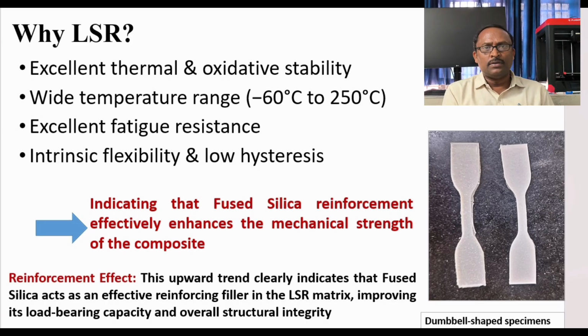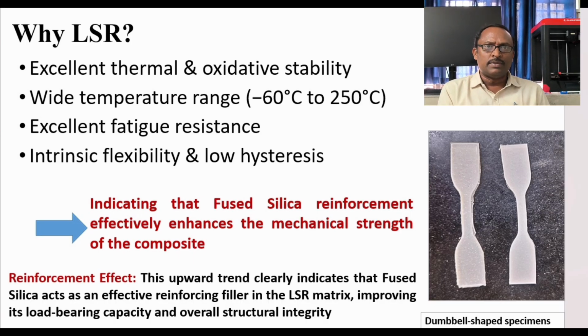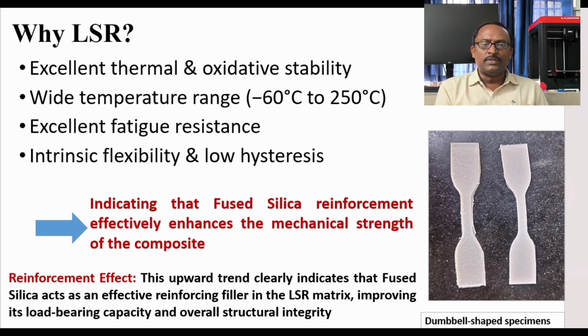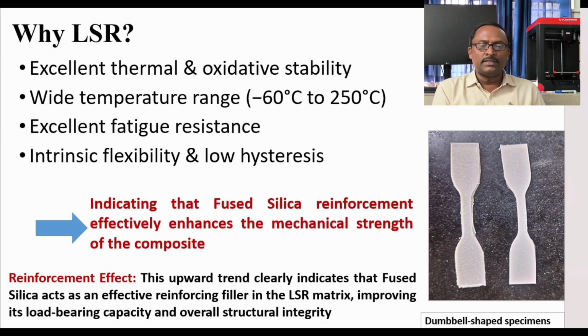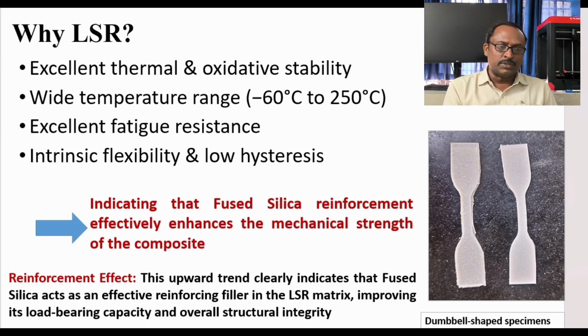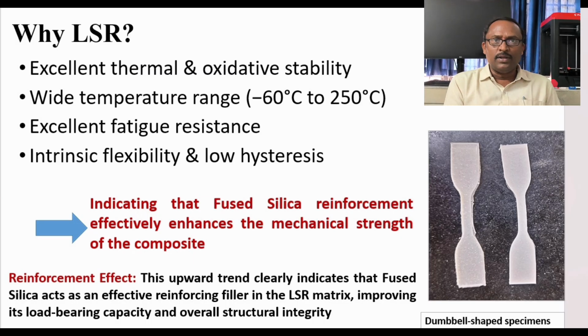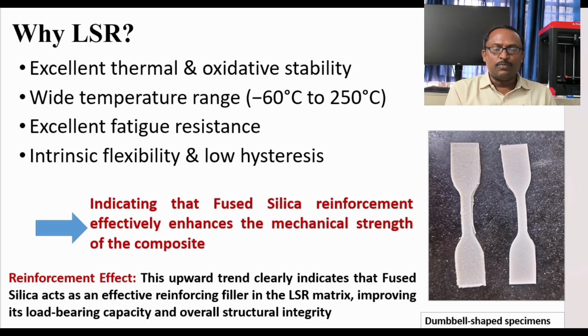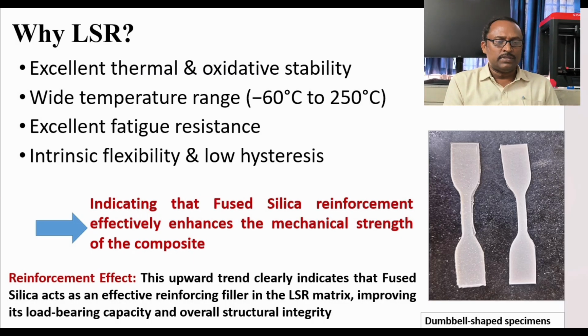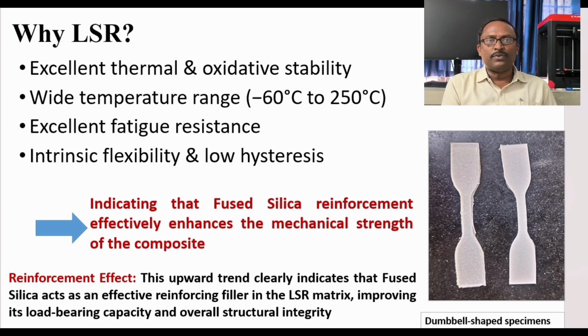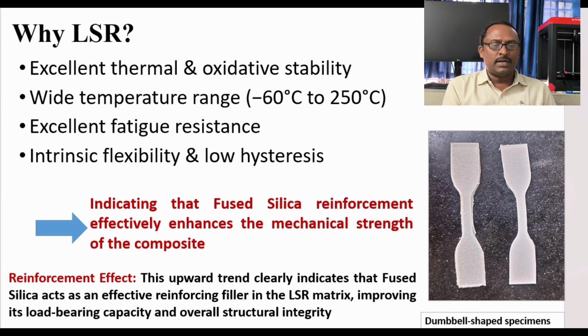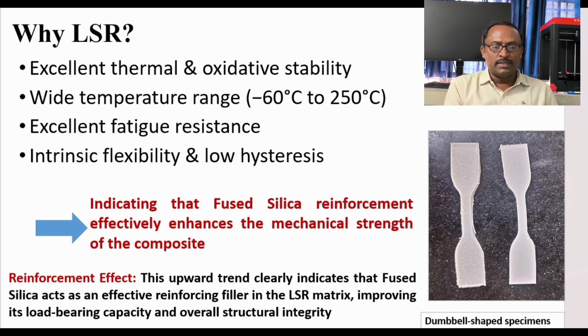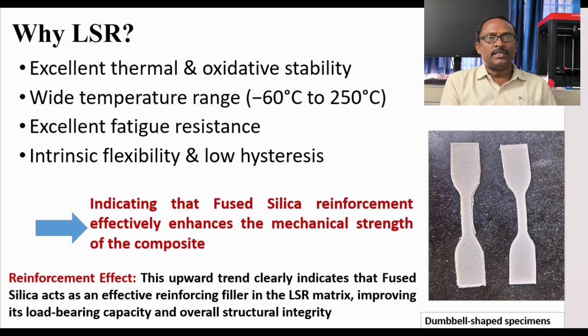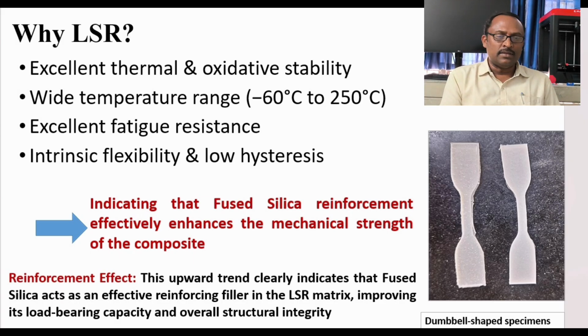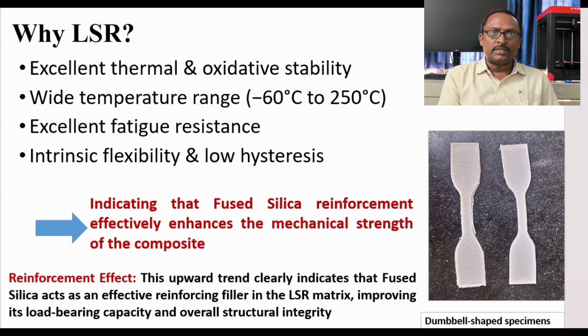That is the fused silica reinforced liquid silicone rubber, indicating that fused silica reinforcement effectively enhances the mechanical strength of the composite. Dear friends, the reinforcement effect and this upward trend clearly indicates that fused silica acts as an effective reinforcement filler in the LSR matrix, improving its load-bearing capacity and overall structural integrity. This is very challenging in the LSR. That's why LSR is preferred in industry.